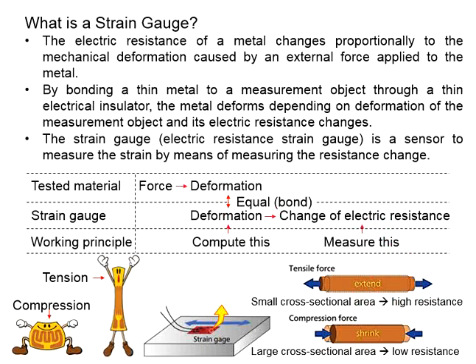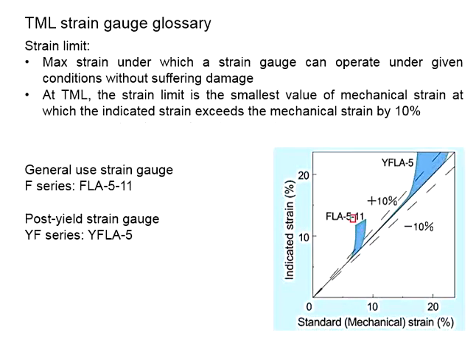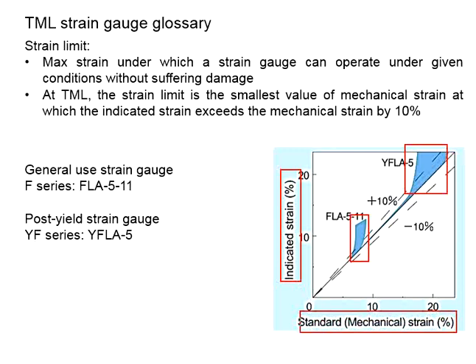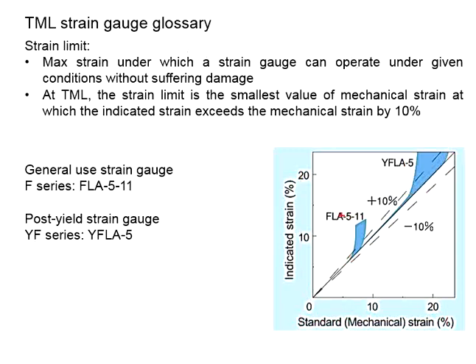With that, reaching a certain limit, the measurement becomes significantly deviated from the actual measurement. This brings about variations between the indicated strain and the mechanical strain. What you see here, you have two types of strain gauge. Before reaching the limit, the measurements can be quite accurate. However, starting from here, for this type of strain gauge, the deviation enlarges.